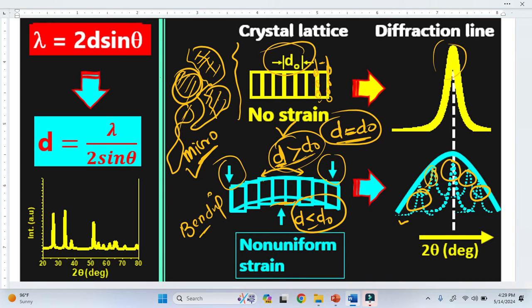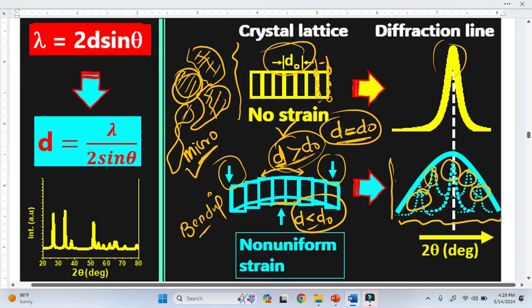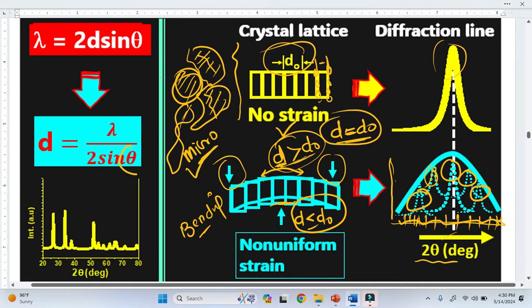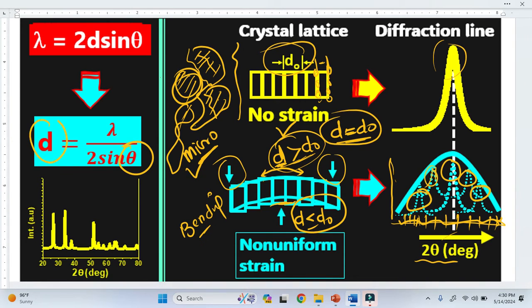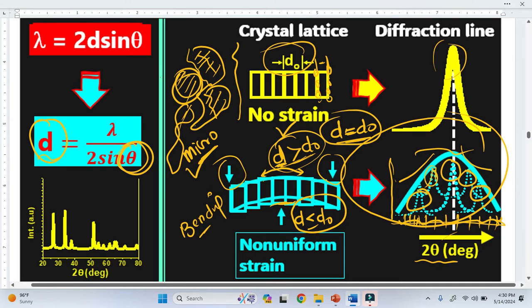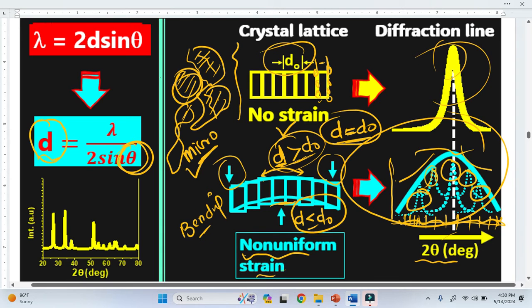XRD gives us the overall result on the two-theta axis. Once we have various peak positions on that two-theta axis, this means the two-theta value is varying. From Bragg's law, varying theta means varying interplanar spacing. Because of that varying interplanar spacing, we get different peak positions. The system has no other option but to broaden the peak. This is how and why microstrain — when strain is non-uniform in a material — makes the XRD peak broaden.